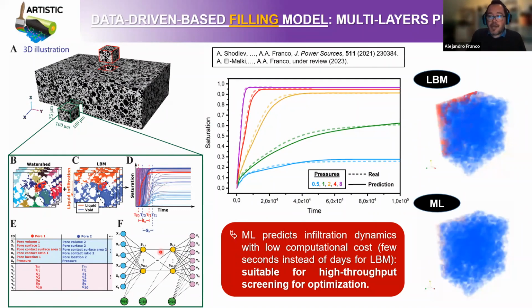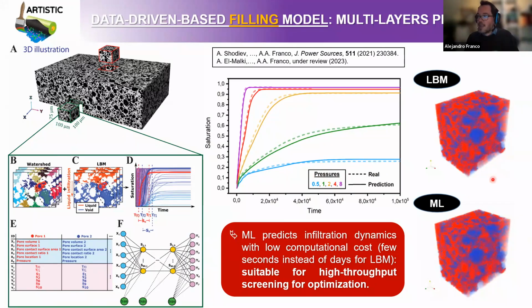And with this data set, we have trained a multi-layer perceptron model, which is nothing more than a kind of neural network model. Thanks to this model, we are able to predict, in good agreement with the results of the lattice-Boltzmann method, which is here labeled as real. We see a very good prediction with the machine learning model of the saturation curves calculated by the lattice-Boltzmann method for different applied pressures. And also, thanks to this machine learning model, we can reconstruct in 3D the trajectory of the liquid electrolyte in the electrode volume, in good agreement with what you get in the lattice-Boltzmann method. So we believe this is very interesting because with very much reduced computational power, you can predict the same results that you get with the lattice-Boltzmann method.